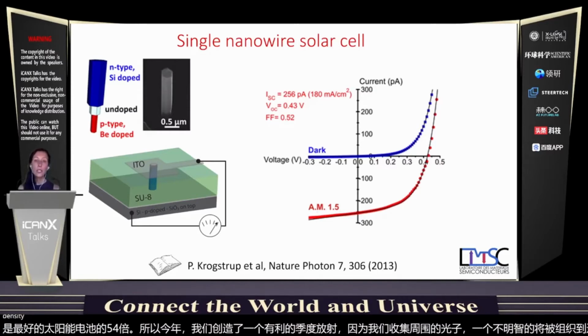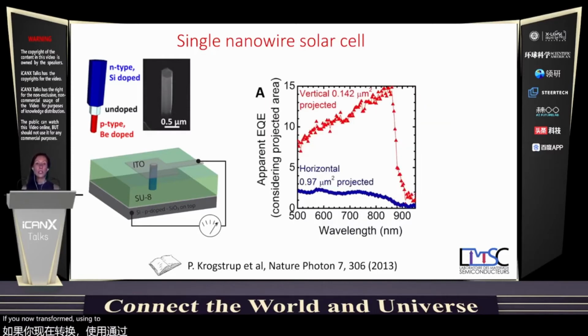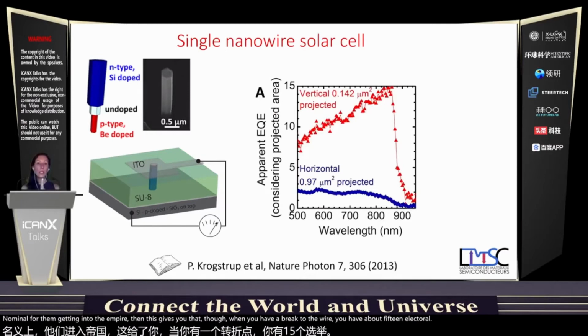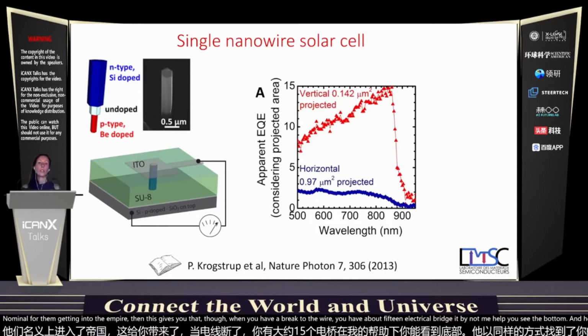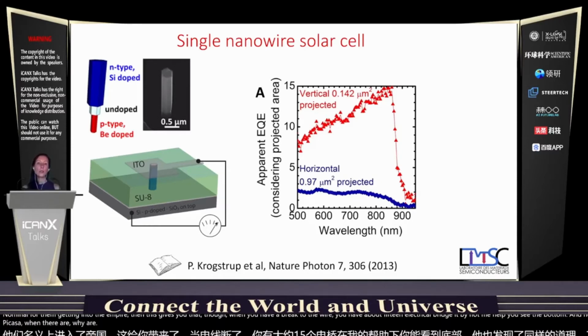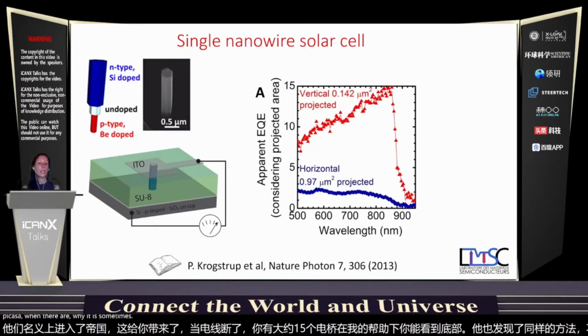If we now transform this into the external quantum efficiency, which is how many electron hole pairs you get by nominal photon getting into the nanowire, then this gives you that when you have a vertical wire, you have 15 electron hole pairs generated by nominal incident photon. And if you have the same wire horizontal, you have much less. And it's because when the wire is horizontal, you collect much less photons than when it's vertical. When it's vertical, you have all these photons that come around and funnel inside the nanowire.